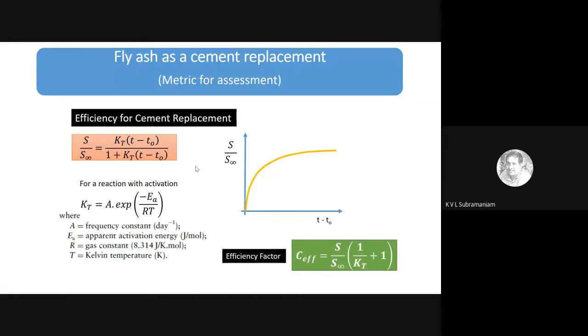with fly ash, then I can actually improve the strength, because what happened in that system is, yes, while I lost some calcium, which went with the cement, I brought in more silicon. And remember that in a cement system, it's a calcium rich system because a lot of calcium hydroxide is produced. So net, I was able to produce more calcium silicate hydrate in the system, which gave higher strength.